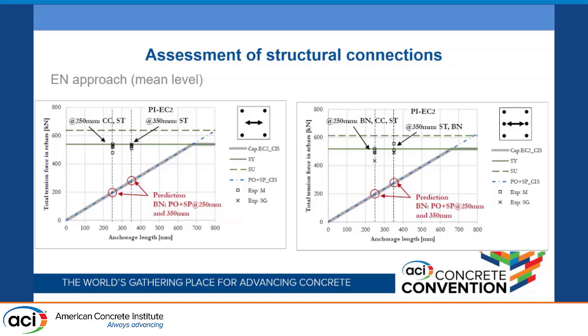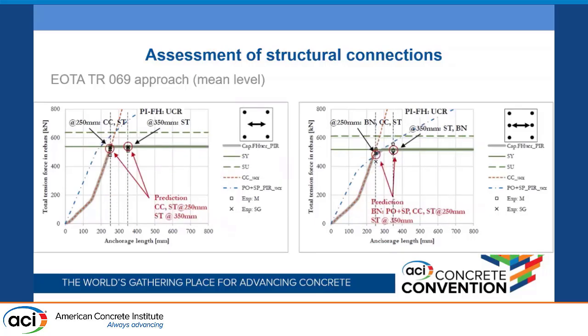So in case of the column foundation joints, the Eurocode formulations were predicting significantly lower values compared to what we got in the tests. And when we use the new approach, which is now in the EOTA TR69, then we are able to predict the failure loads and the failure modes rather accurately. So that was the kind of background and the whole story, how it developed.